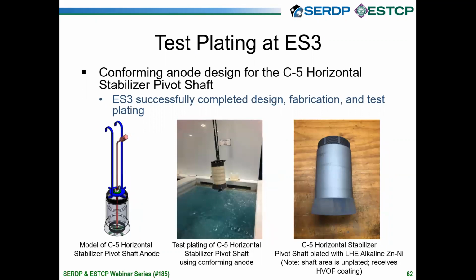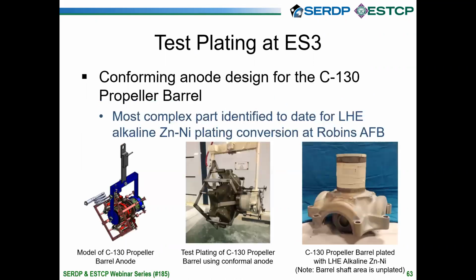So this is the C5 horizontal stabilizer pivot shaft. You can see in the middle picture that we've got part of it masked off. That's either hard chrome or HVOF plated, depending on where it's at in its life cycle. Again, the picture on the left just shows where the conforming anodes are at. Without those nickel rods in the center, you would not get any plating on the inside. So this is just required in order to get nice even plating in accordance with that specification. You can see the fully plated part on the right after it's gone through, everything plated nice and evenly. We'll demonstrate that same thing once we go to perform that Dem/Val.